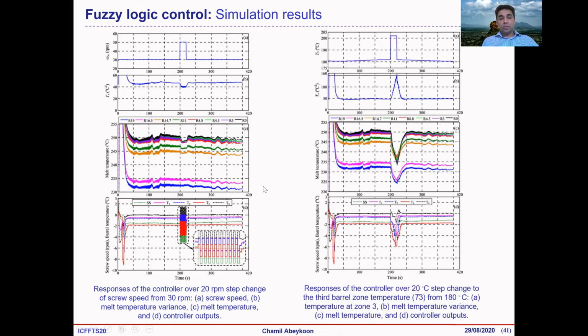This is with a 20 RPM step change. And here we introduce a disturbance by introducing a step change to the third barrel set temperature, and still the process comes back to normal operation, without becoming unstable.